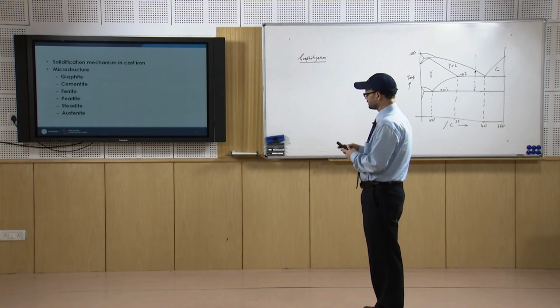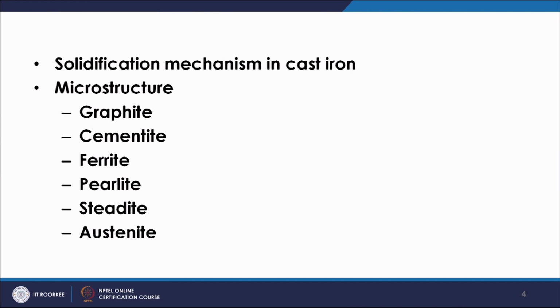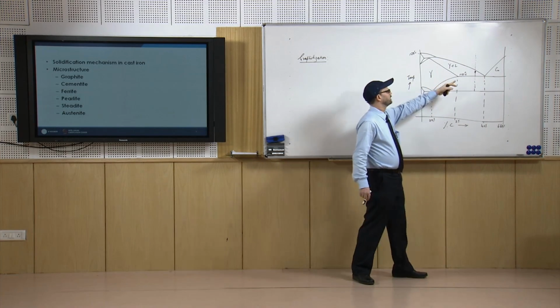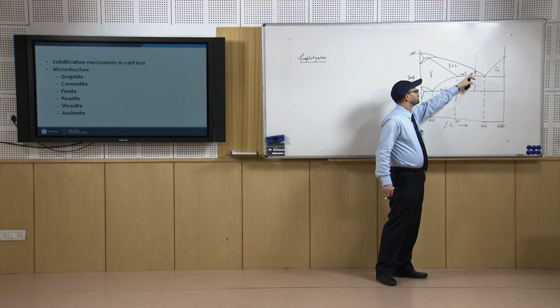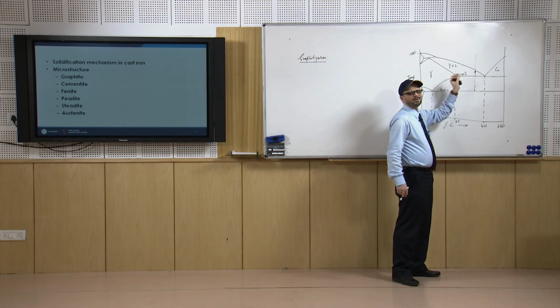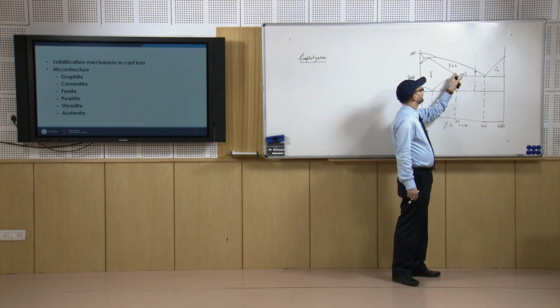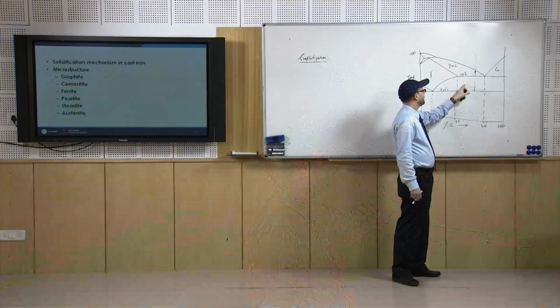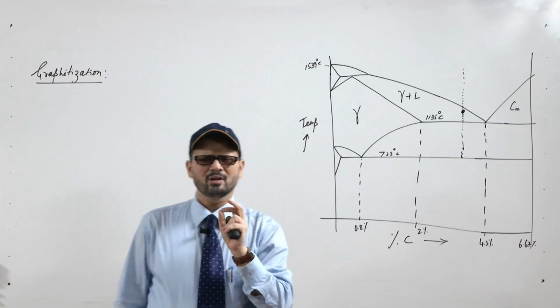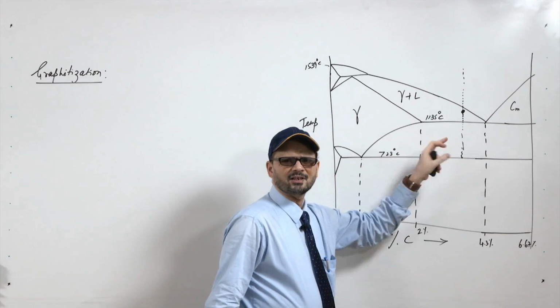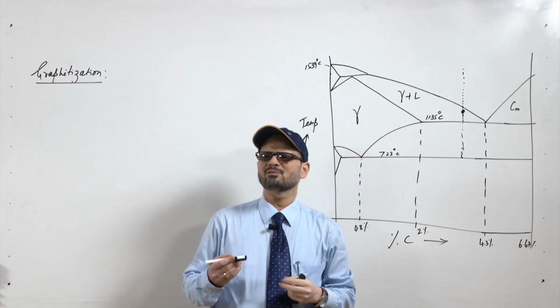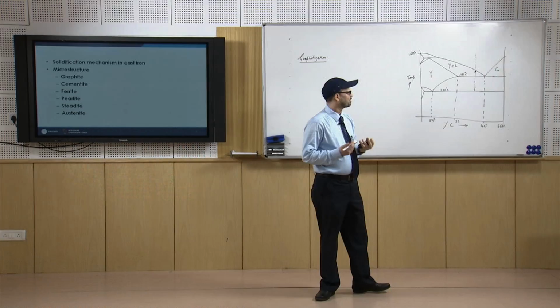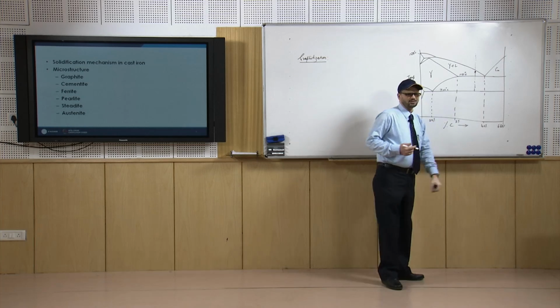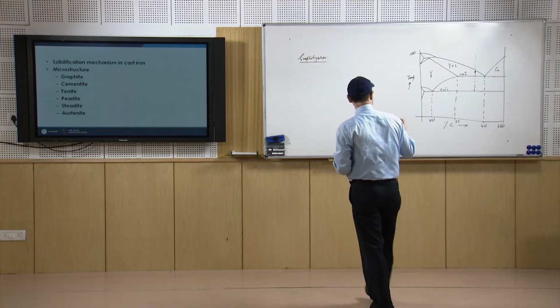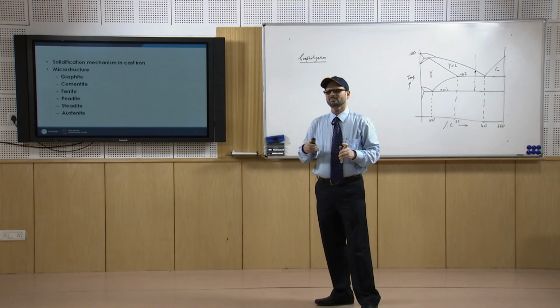Now, you have to understand the mechanism of solidification that we have already discussed, how this solidification takes place when we go below this temperature, how the excess carbon will come out of the solution, and then this austenite will also lose the carbon. Finally, depending upon the cooling conditions and also the presence of alloying elements, this carbon will either be in the form of graphite or in the form of Fe3C. So, this way at room temperature you may have different matrix, maybe pearlitic, ferritic, and you may have the carbon in different forms.